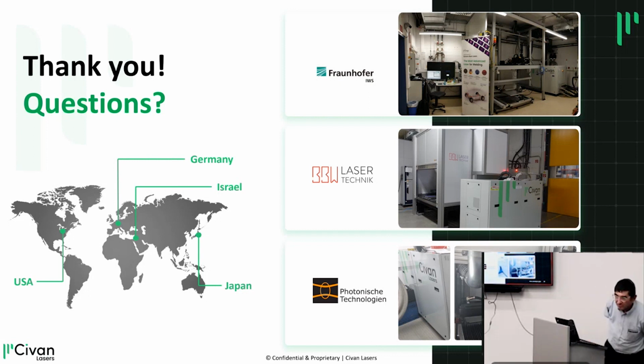Question about the maximum gap you should have. We can probably go up to 1 millimeter or so, but it really depends on many parameters. There are two elements to the gap. One is what the laser will do, and with the laser we can go to a longer focal distance and cover a larger area. But also in terms of the weld, if you have too much of a gap, at the end of the day you're going to have underfill, just missing material, even if you bring it from the side. But we can overcome a lot of it.